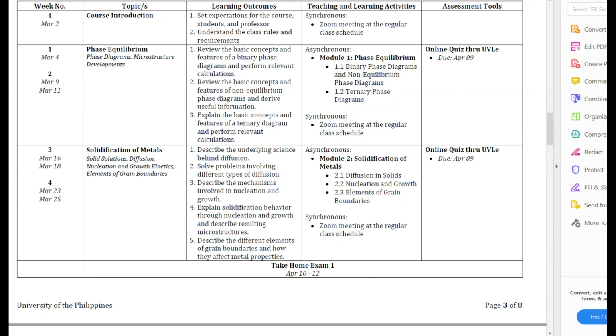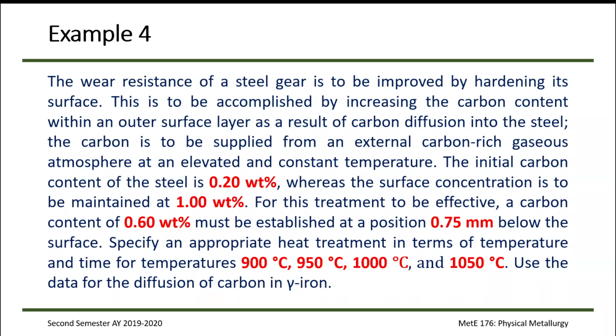Okay, so let's start with this problem, no? So meron daw tayong isang steel gear, tapos gusto natin i-improve siya by hardening its surface. And again, I think nasa MetE176 nyo dito, no? This process is known as your case hardening process. And specifically ito, you are using carbon, no, to harden the surface, which is the main way we can harden steels, no, increasing the carbon content. Okay, so sometimes this is known as carburization, and meron tayong sinusupply na external carbon-rich gaseous atmosphere at an elevated temperature and constant temperature. So it's elevated para mas mabilis yung diffusion niya, no? So if it were not elevated, then baka it occurs at a very slow rate.